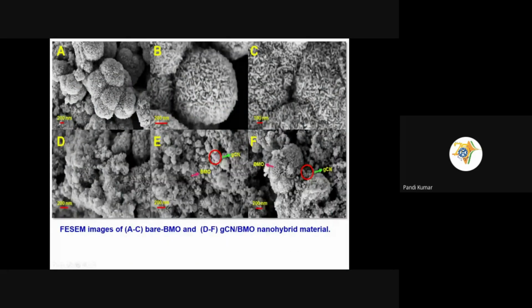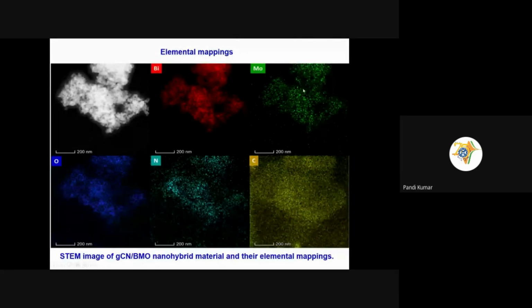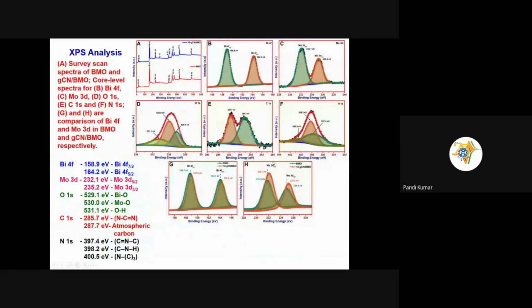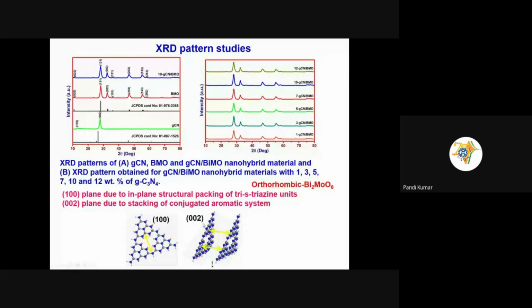So this is the pristine bismuth molybdate. This is after modifying, forming a heterojunction with the graphitic carbon nitride. Here you can see that the graphitic carbon nitride formed over the surface of the bismuth molybdate. Then the elemental mapping clearly confirmed the different elements present in the heterojunction material. In the XPS analysis, the shift in the binding energy compared with the pristine material and the heterojunction composite material reveals the formation of the heterojunction and the strong interaction between these two materials. When we talk about the crystal property of this material, after adding the graphitic carbon nitride, it does not alter the crystalline property. That is the orthorhombic structure of bismuth molybdate.